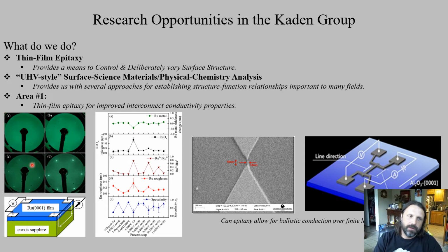In this case, rather than a double slit, the crystal termination of the surface itself is the slits. And instead of a one-dimensional array of those slits, you have a two-dimensional array of unit cells that are formed by the crystalline structure. So the crystalline structure gives you a pattern that instead of a one-dimensional series of lines is a two-dimensional series of points. The points here tell you about the structure you have. In this case, it's telling us that the ruthenium we made is definitely single crystalline and very well defined. It's very sharp spots, hexagonal symmetry.